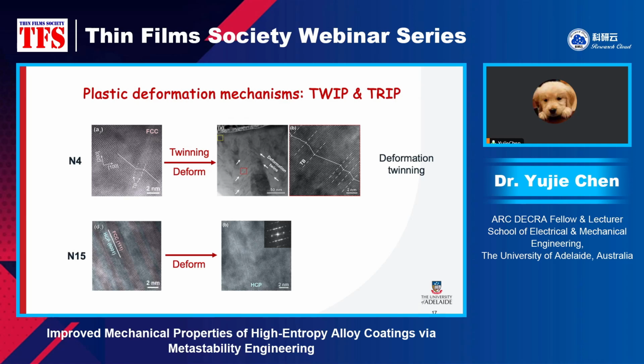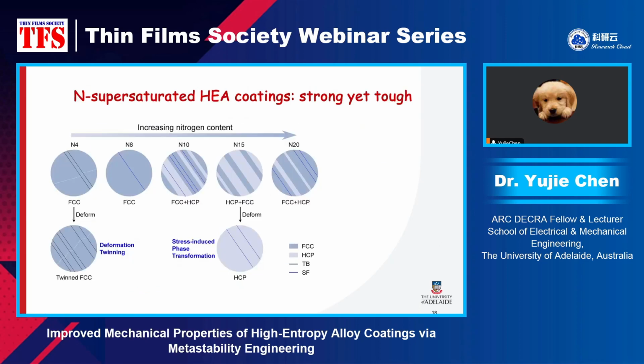Although we have added a high content of nitrogen, the high-entropy alloy still can deform plastically like pure metallic material. With its ability to undergo large plastic deformation combined with the massive solid solution strengthening caused by the high nitrogen intake, the material shows an excellent combination of hardness and toughness. So it's a quick summary of this study.